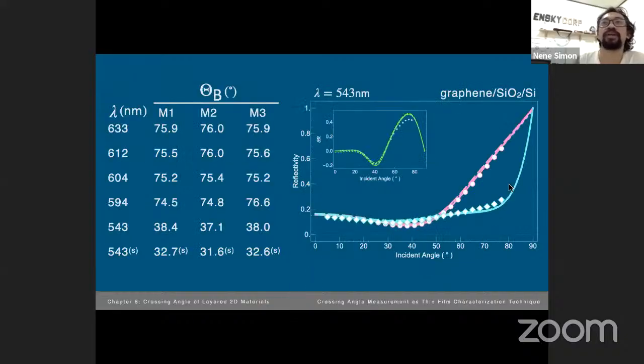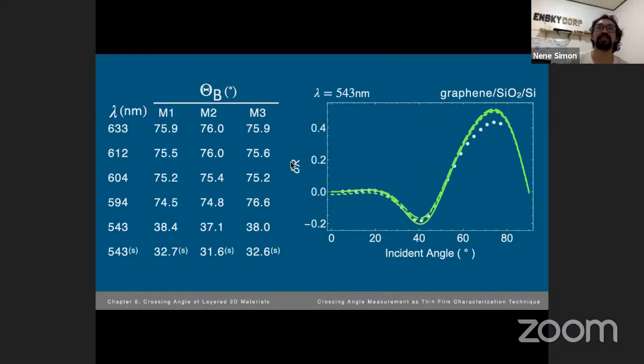And so instead of using the reflectivity magnitude, I tried analyzing the sample using the pseudo-Brewster angle position. But as you can see here, the position of the pseudo-Brewster angles for different wavelengths are almost the same. The three models are predicting almost the same position, and this is within the uncertainty of our measurement. The uncertainty again is 0.5 degrees. So the position of the pseudo-Brewster angle cannot be used to discriminate the three models, which led us to focus on the degree of polarization.